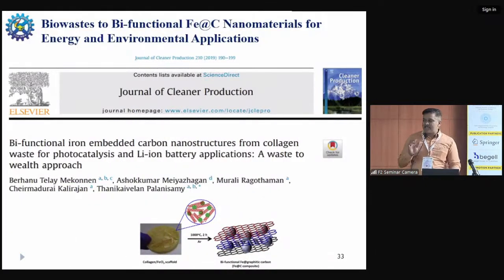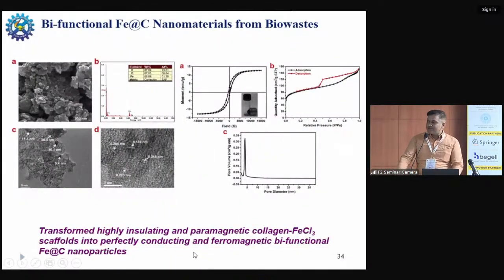And in this example, what we did is we treated simple iron chloride with collagen and then subjected it to high temperature treatment. And here we transformed the initial material, which is highly insulating and paramagnetic because of the iron chloride, and when we subject it to high temperature, we were able to convert it to a perfectly conducting and highly ferromagnetic bifunctional material, where the iron particles are surrounded by carbon or graphene layers.